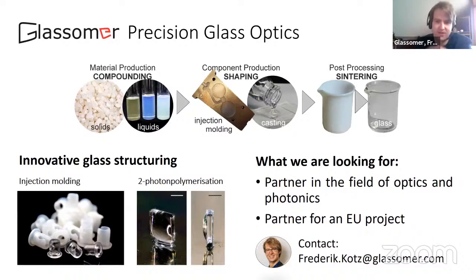No, we don't have any micro crack processes. Our standard material is fused silica glass. That's also because we have that low thermal expansion. It's 0.5 times 10 to the minus 6. You can basically heat it up as fast as you want and cool it down as fast as your oven can go. We even did microwave sintering of that, and you never will face any issues of internal stresses. If you make multi-component glasses, you have the same as for all glasses. You basically have to temper at some point.